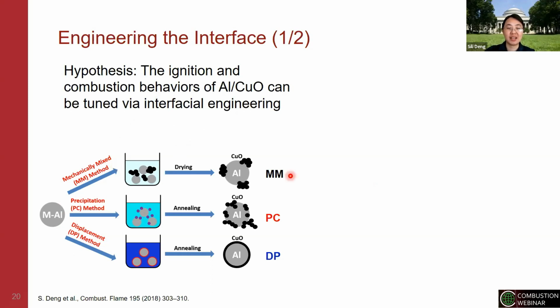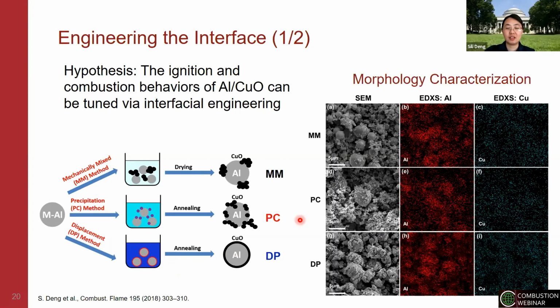This is a traditionally mechanically mixed particles, and this is a precipitation method in the liquid phase. And this is a displacement method using the electroless deposition of the solvent to the surface of the energetic materials. And you can see clearly the manufacturing method or the synthesis method has an influence on the morphology of the obtained composite of energetic materials. The coverage is different, the dispersion is different, etc.